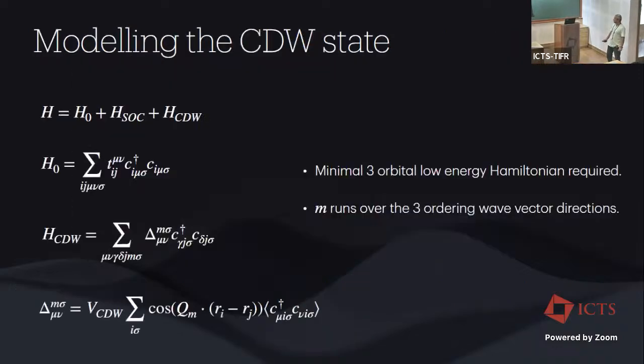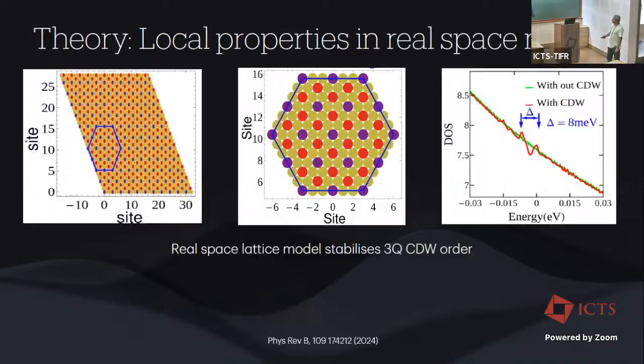vector. Now, to model the CDW state in real space, I'll just quickly go over this. We convert it to a lattice model, including a CDW instability. We calculate self-consistently by having a pairing term, and this m factor that you see out here goes over the 3 wave vectors in the 3q CDW state. So then for this lattice model, when we look at it, you can stabilize on a lattice this 3q CDW